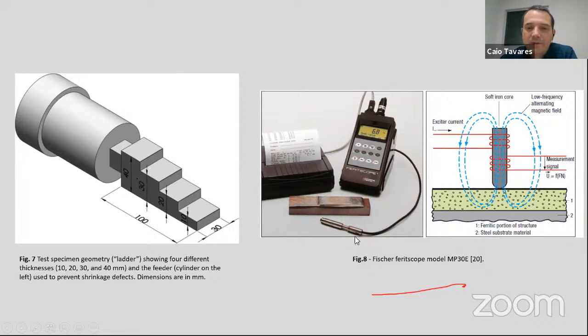We measured the ferrite with this equipment called the ferritoscope. The intention was to evaluate how it works. This ferritoscope has a probe, and by induction, a magnetic field is created here, and according to the ferrite that you have here, since ferrite is magnetic, it creates a different signal, and you read it here in voltage. So according to the voltage, you get a different percentage of ferrite.